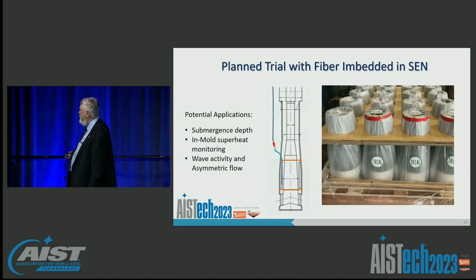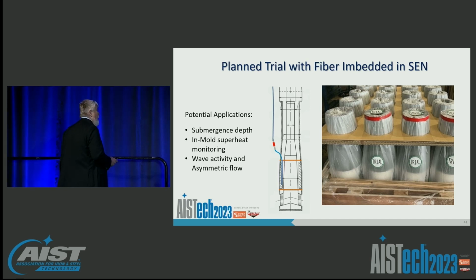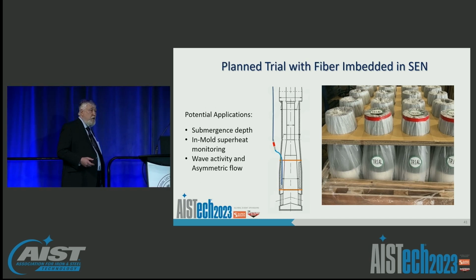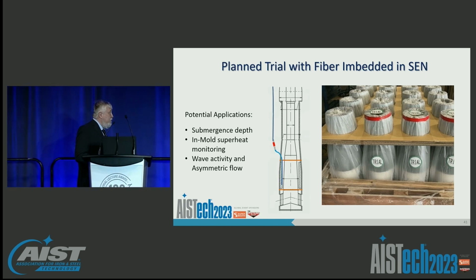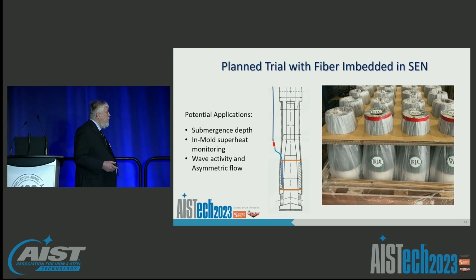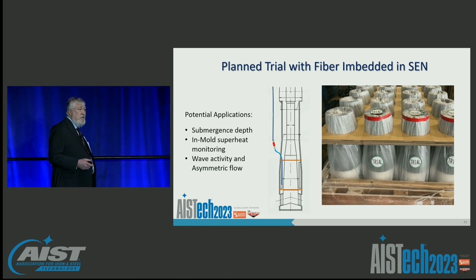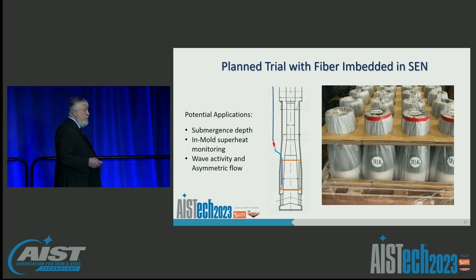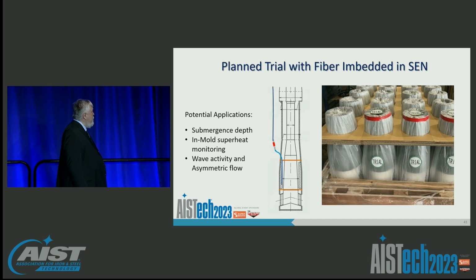Our holy grail is actually to demonstrate these in a commercial refractory. So we've actually had some trial nozzles made that are going to be put into a commercial test here in the next, actually, month or two, where the fiber is embedded into the sidewall of a submerged entry nozzle, and we can actually measure the temperature gradients along the length of the SEN for ultimately things like wave measurement, submergence depth monitoring, and so forth.